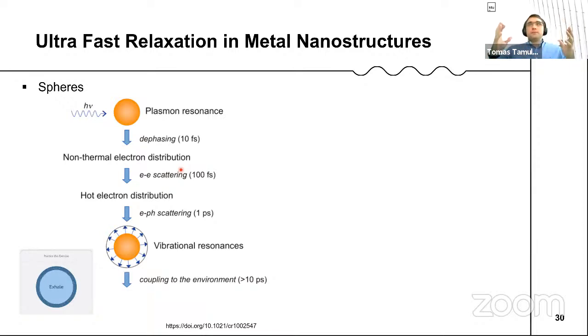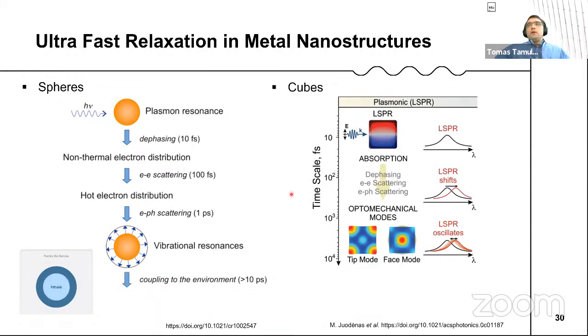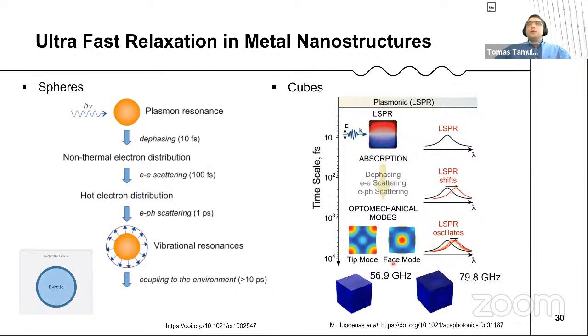The nanoparticle expands. It still has the same number of electrons inside, so the energy density of the electrons changes. And when it expands, it is willing to contract again, and it starts to work as a spring. And if we have cubes, like in our case, and you have this localized surface plasmon resonance, this LSPR position should be oscillating together with this oscillating nanoparticle. And we have some complicated optomechanical modes that are induced by the femtosecond laser, and they look like this for a certain size of a nanoparticle. So this is the tip mode, and this is the face mode, and how to follow these things optically.